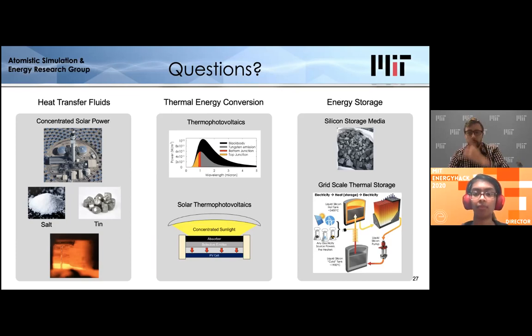Yeah, so we designed the thermal storage component, so the silicon tanks, or in the case of TEGS 2.0, the graphite blocks, to lose about 1% of their thermal energy per day. So this enables daily and weekly storage pretty nicely. If you wanted to store energy for a very long period, like over the course of months, it probably wouldn't be the best technology because, as you mentioned, you'd have to continue expending energy to keep it topped up. But on the order of days or weeks, it's really not so much of a problem.